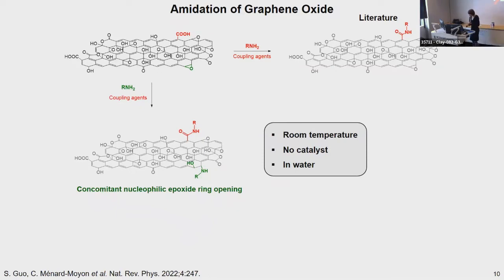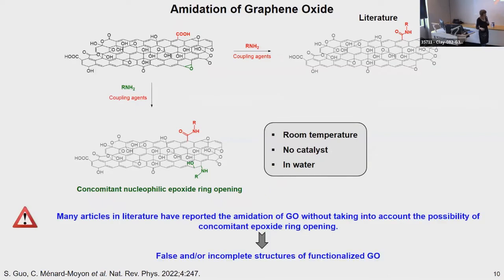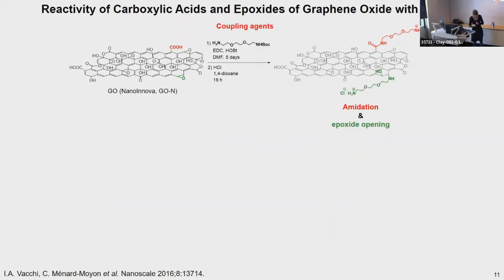But the main issue is that in the literature, there are many articles reporting the amidation of graphene oxide without taking into account the possibility of this concomitant epoxide ring opening. So this leads to false and incomplete structures of functionalized graphene oxide. So we investigated this reaction in more detail.